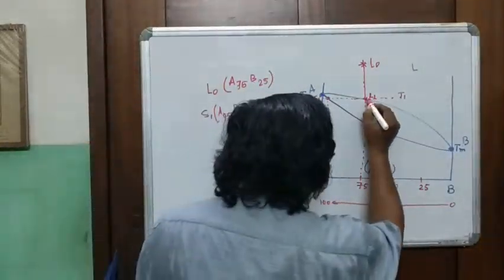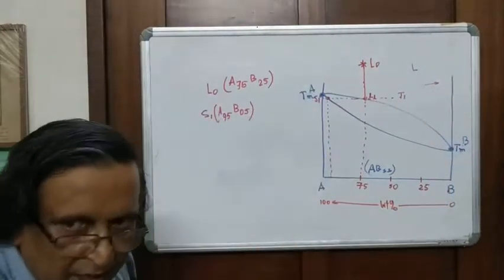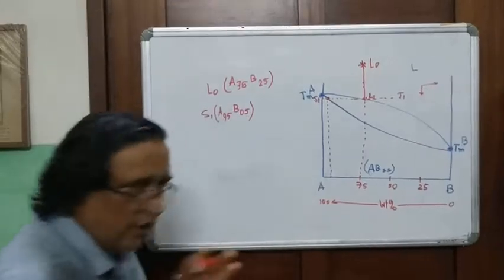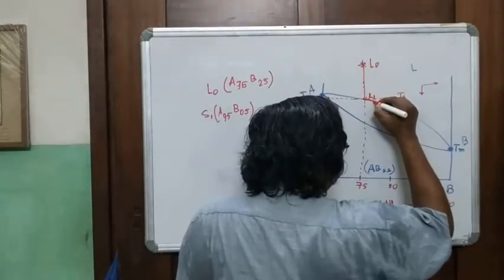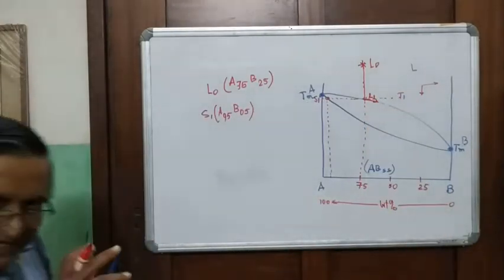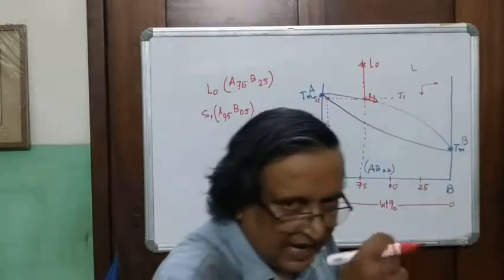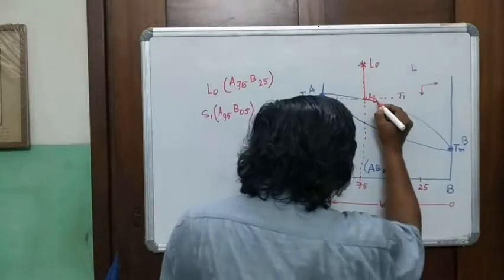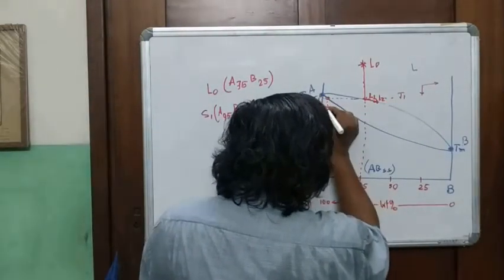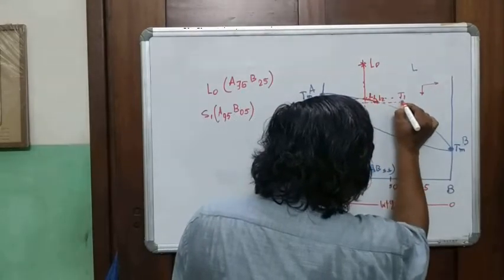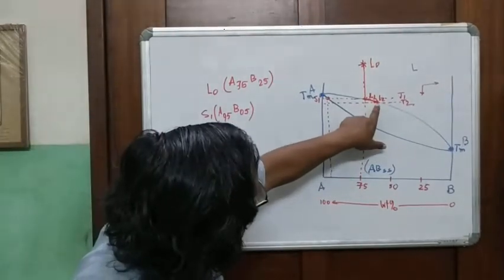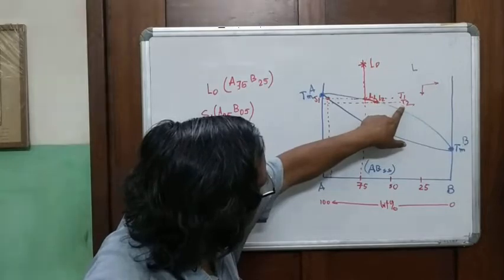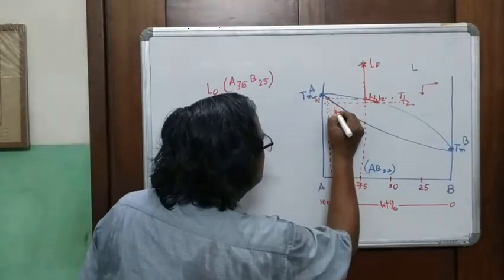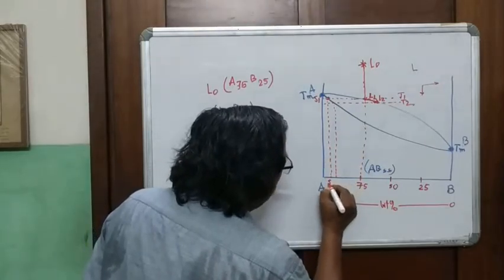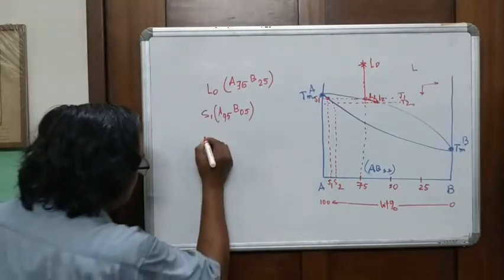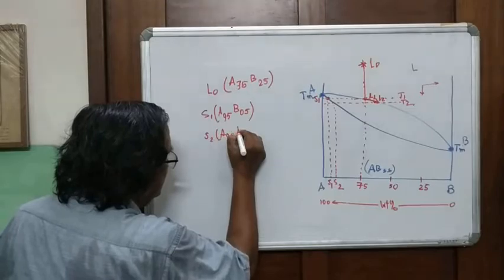So the liquid composition moves in this direction, but at the same time you have cooling, so this is also the direction. Effectively, the liquid composition moves along the liquidus, and yet you have an equilibrium between the crystallized solid and the melt. So here you have a new liquid composition L2 at temperature T2, and this line intersects the solidus and gives you the composition. This one was S1, this one is S2. And S2 is A90 B10.